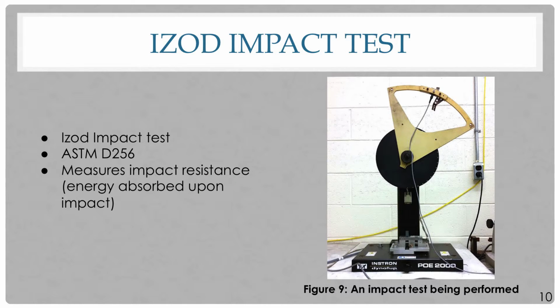The next test we performed was an IZOD impact test based on ASTM standard D256. We prepared our specimens by notching and measuring them, and each sample, of which there were 2, was composed of 10 specimens each. In order to perform our impact test, we placed a specimen in a vise and swung a pendulum in order to fracture the specimen.